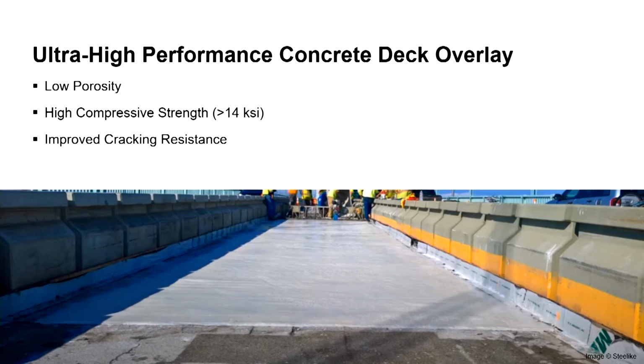So DDOT expressed interest in the use of UHPC for some of these repairs, and so we're moving forward with a UHPC deck overlay at this time for the structure. In the testing of the deck that was done, they found evidence of some ASR, mostly in a shallow condition. So UHPC will be able to be a more shallow overlay, but since it's such a low porosity material, it'll also provide that protection from the chlorides in the de-icing salts. One of DDOT's other concerns with the overlay is they've experienced a lot of cracking in overlays done with more traditional materials. So they're interested in the improved cracking resistivity that you can get from a UHPC material.